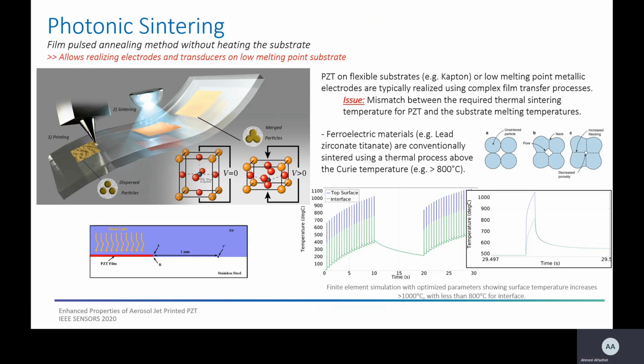PZT film was photonically sintered in this work under an ambient atmosphere for a very short period of time. A xenon lamp was utilized that emits broadband sub-millisecond high-intensity pulses that control the heat exposed to the film. Traditional thermal sintering in a high-temperature furnace was also carried out to provide a sample for comparison, at 1000 degrees for 1 hour.